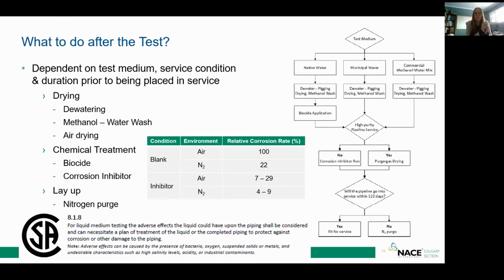And so if you just leave it straight with air, you're going to get all the corrosion that you could possibly have in your line. You could have top of line corrosion, you could have bottom line corrosion. You could really end up with quite a mess. Now, if you purge it with nitrogen, you can reduce that quite substantially, almost a factor of five down to about 22% of the same corrosion rate.